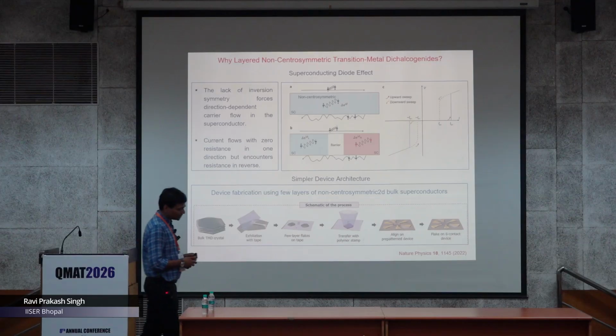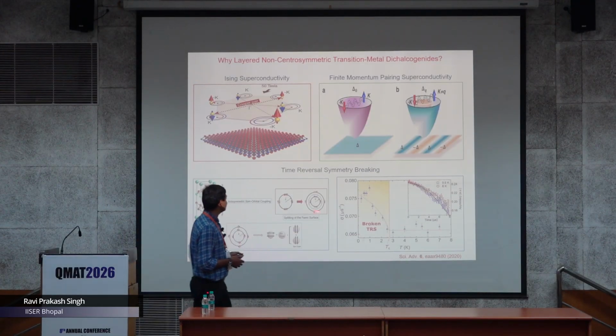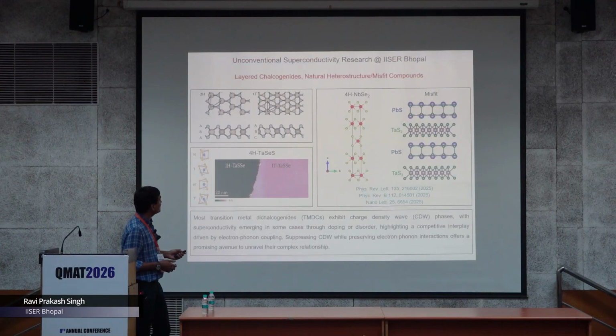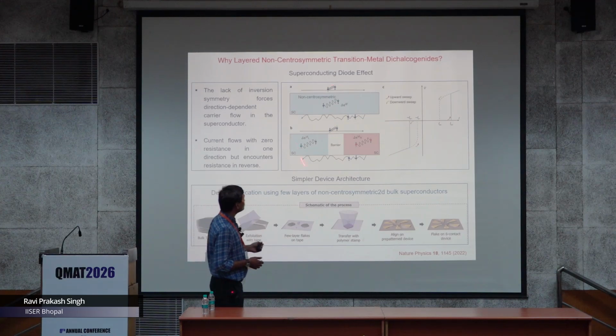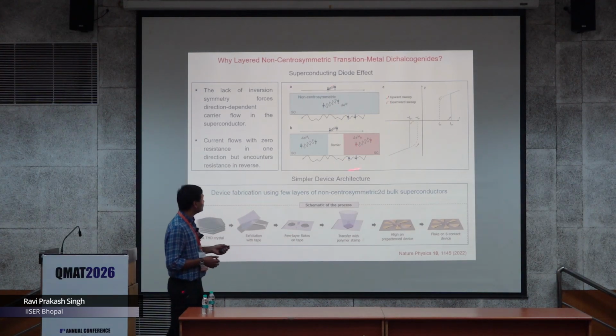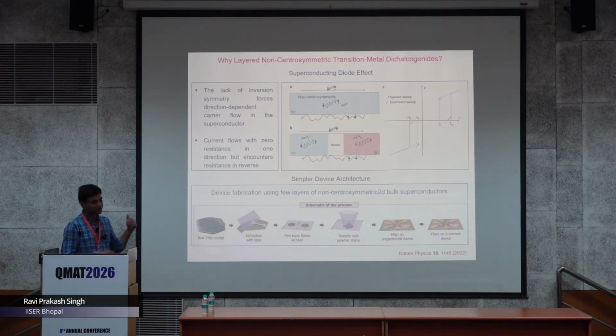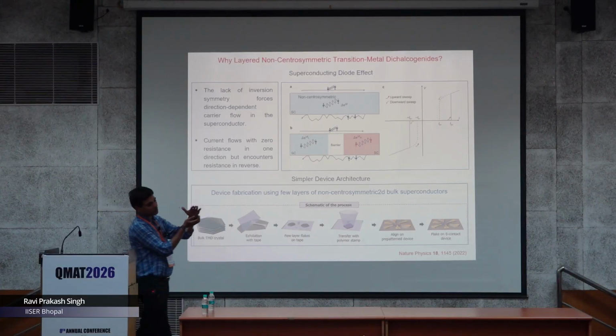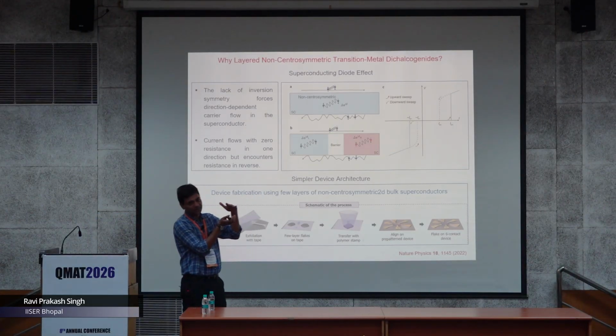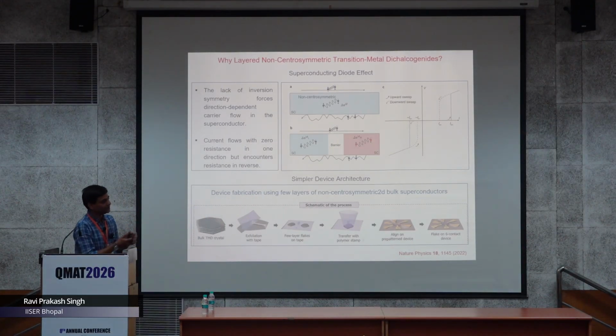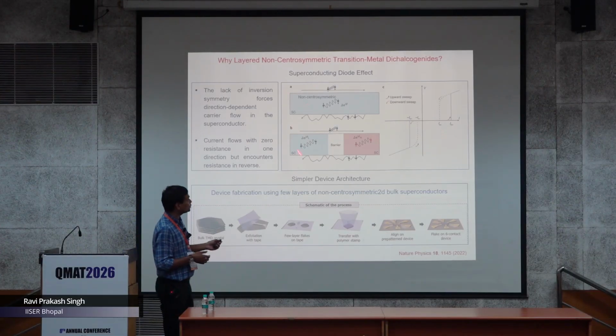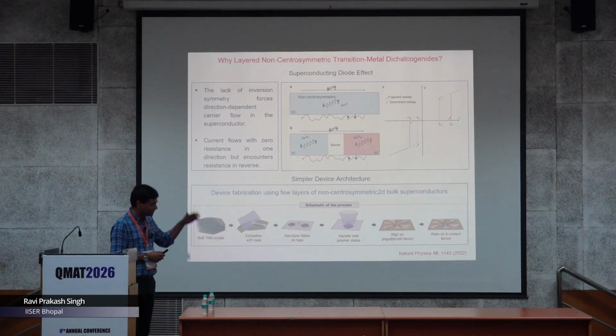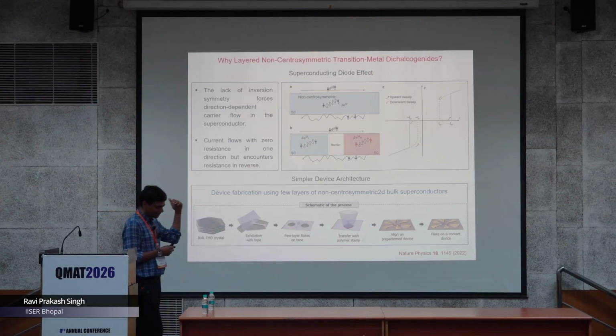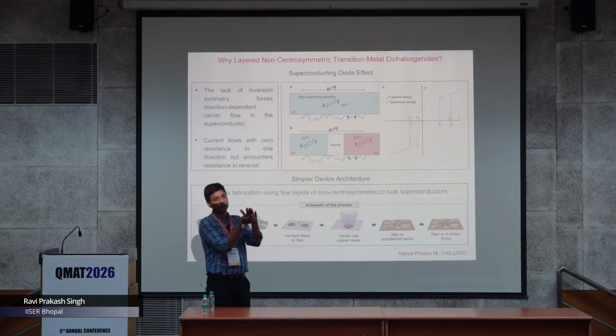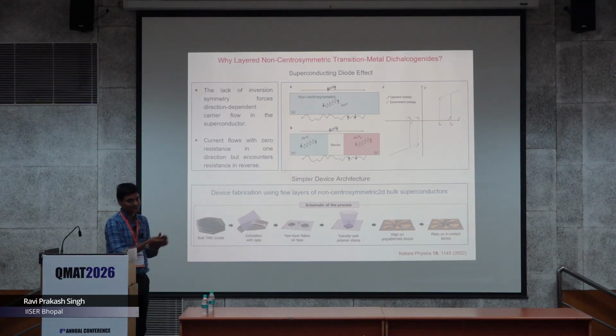And also we are trying to engineer these layered materials to realize the diode effect in these non-centrosymmetric systems, because we can weaken the interlayer coupling and SOC is already very high. So we are expecting at very low temperature we can get these superconducting diode effects, which generally people are able to see in few layer devices.